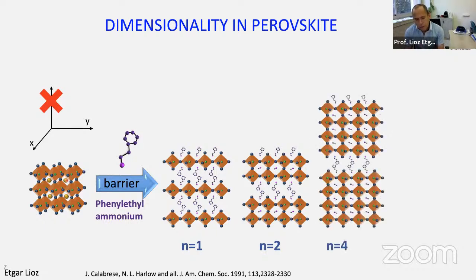The easy part, because it's coming from solution, is that you can create a pure 2D material like N=1 here very easily. But, and this is the disadvantage, because we are making it from solution, it's really hard to control, once you go to N=4 or 5 and more, how many layers you really have inside. Probably it's quite a mixing of several layers. The idea behind using low dimensional perovskite is that when you use an organic cation, it has some hydrophobic chain, which gives some resistivity to humidity to the perovskite, and this is something we want to improve in terms of stability of this material.